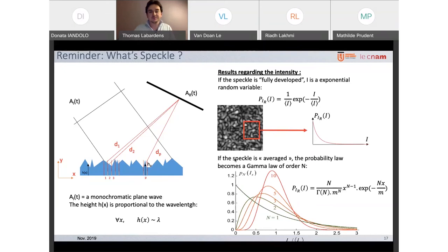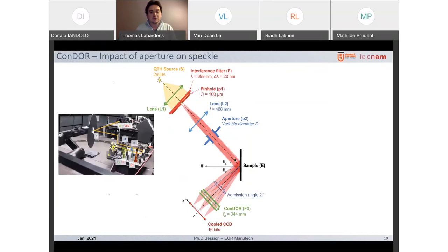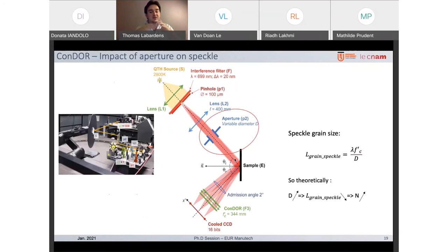Now, to introduce a critical parameter of our study, we need to look at the aperture. Indeed, the aperture of Condor is directly linked to the speckle grain size. As we can see, we have the diameter of the aperture right here, and the speckle grain size directly depends on it. If the diameter is larger, then the speckle grain size is thinner, and the speckle is a bit more averaged, and then the order of the gamma law we just presented gets higher. So now let's look at some measurements.